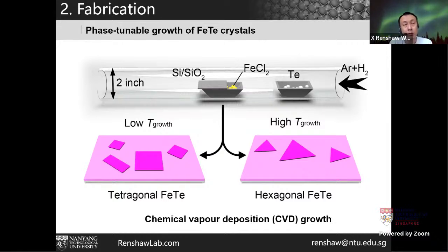Although the schematic of the CVD looks very simple, if you really have some hands-on experience with the CVD, you will realize it's sometimes very nasty, right? Because there are different temperature ranges at different positions or locations of the tube, the flow rate, small contamination, temperature gradients, and the temperature ramping up and ramping down rates, all can have a dramatic impact on the CVD. Now, for this growth of FeTe, we try to keep everything else as stable as possible, and then we vary the growth temperature to see, for different temperatures, what kind of phases we can get.